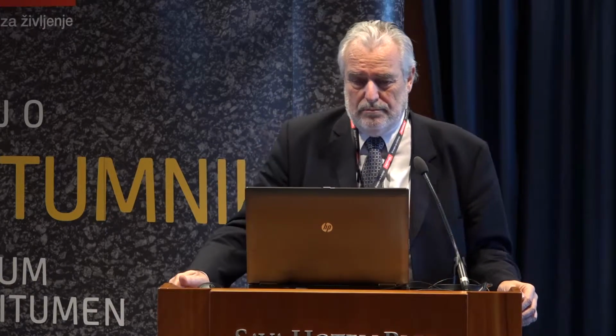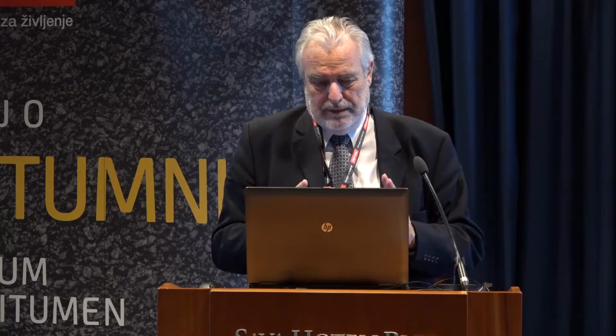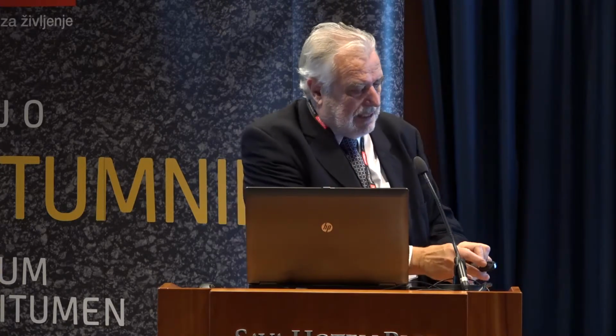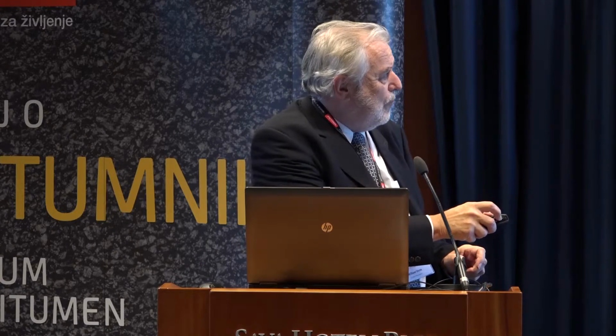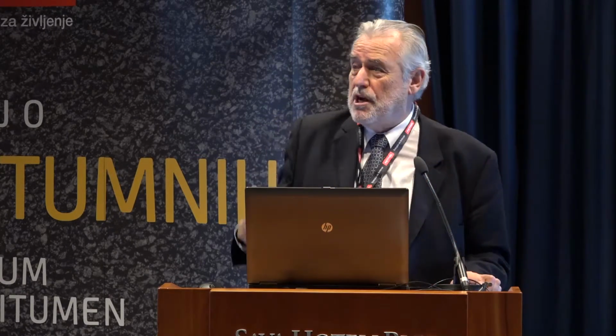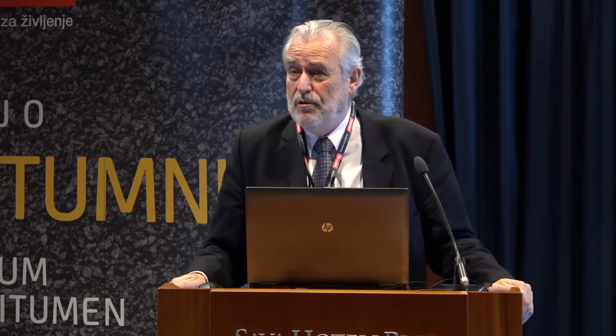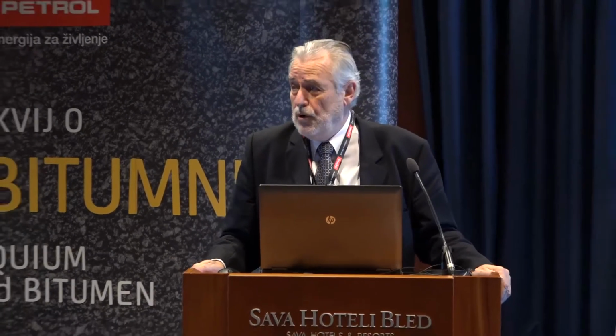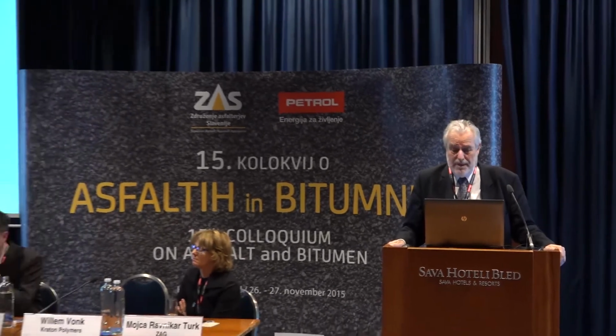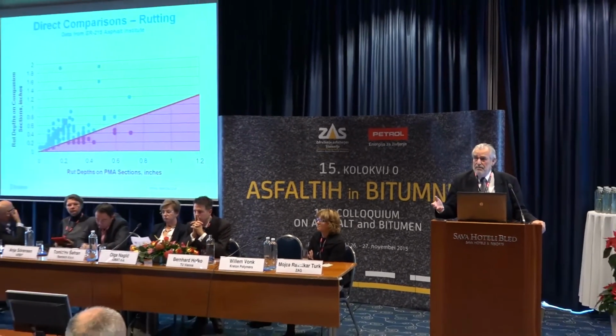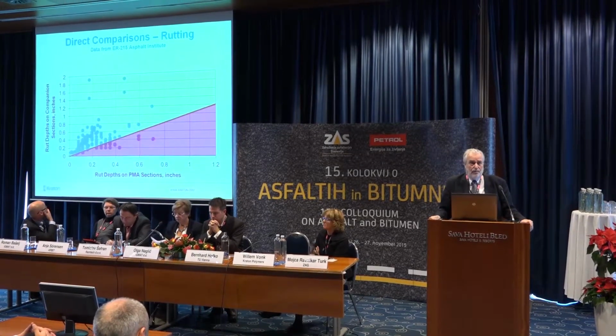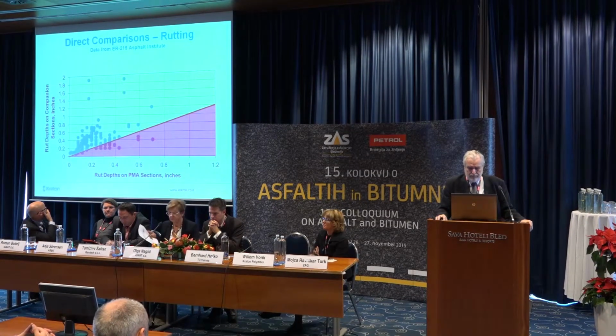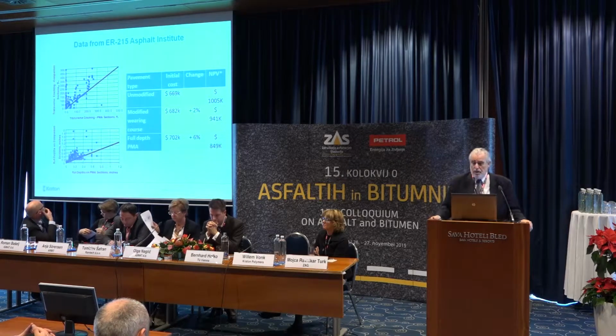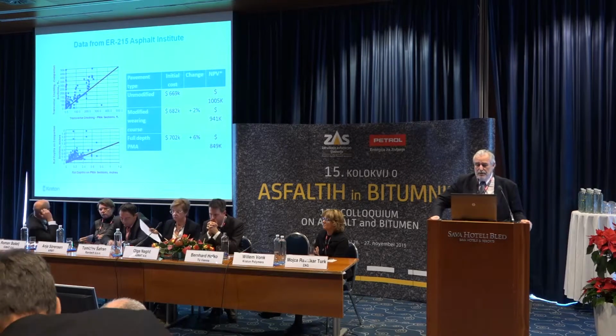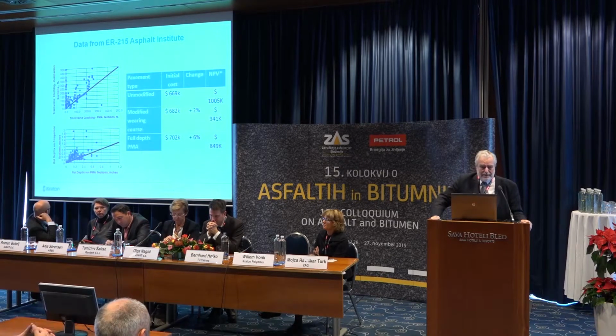This is a direct comparison on rutting. Now, here is the line of equal behavior. If the dots are above that line, then the performance of the PMB is better. If they are below the line, the performance of the PMA is worse. As you can see, most of the dots are above that line of equality. They've also looked at thermal cracking, they've also looked at rut depth and fatigue.